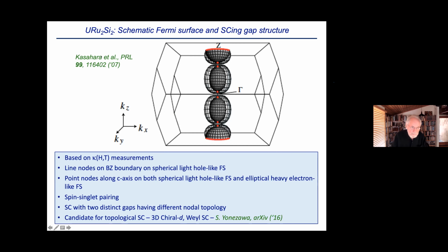superconductivity. This is from the work of Kasahara and co-workers. It's based on thermal conductivity measurements as a function of field and temperature. So as you can see, there are line nodes on the Brillouin zone boundary on the spherical light hole-like Fermi surface. So these are the line nodes here and here. And then point nodes along the C-axis on both the spherical light hole-like Fermi surface and the elliptical heavy electron-like Fermi surface.